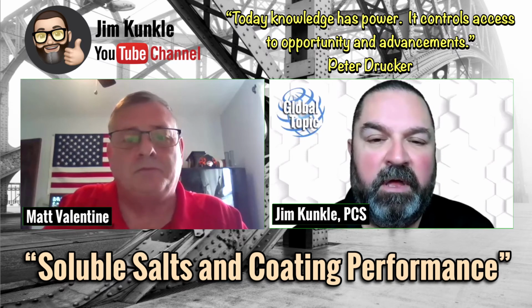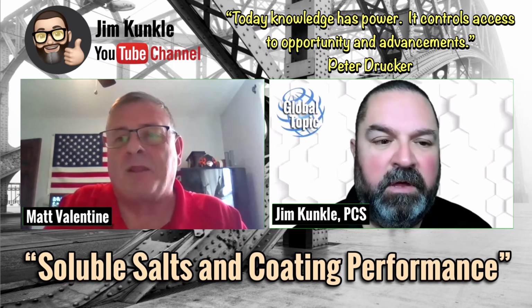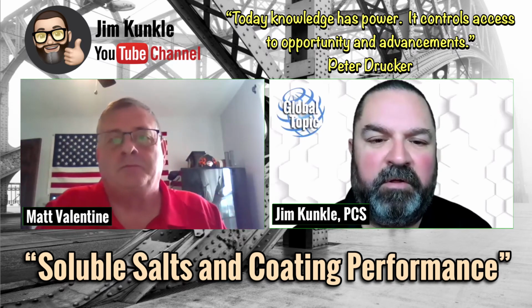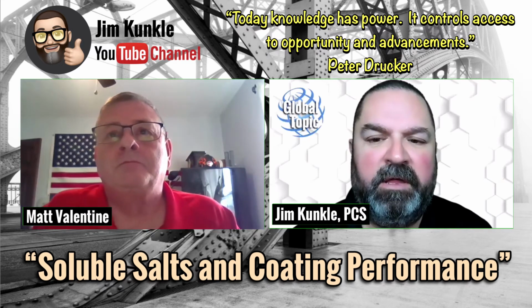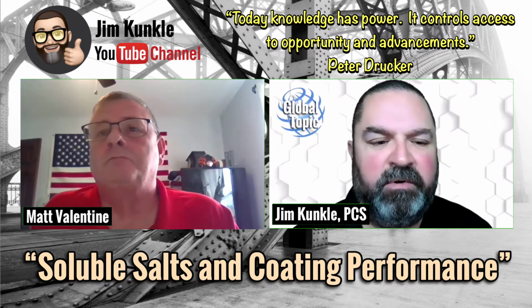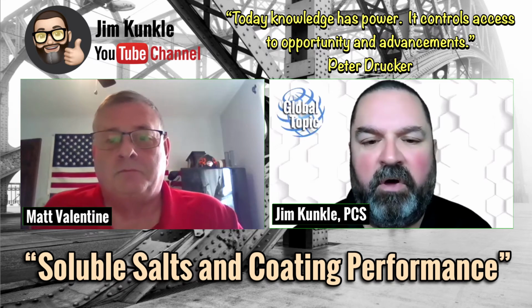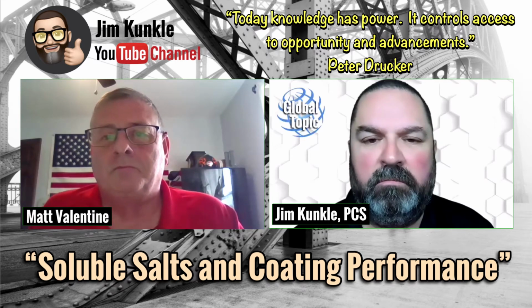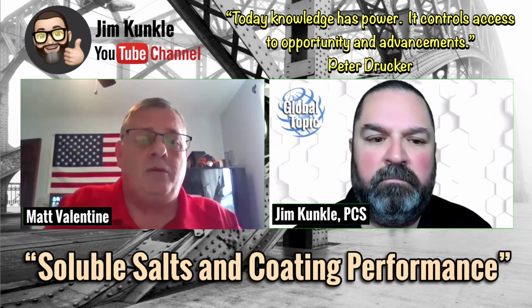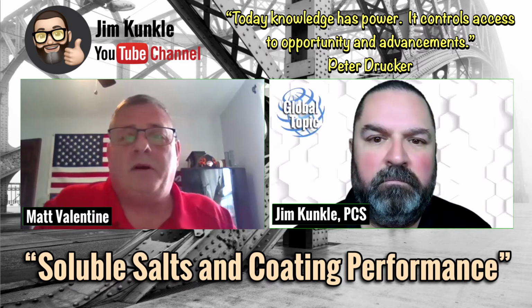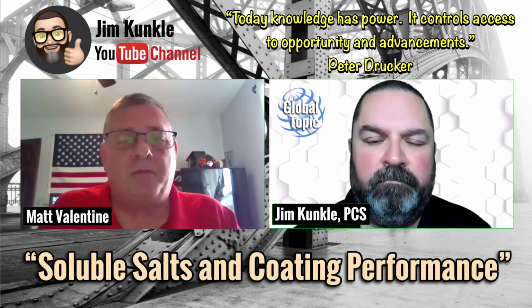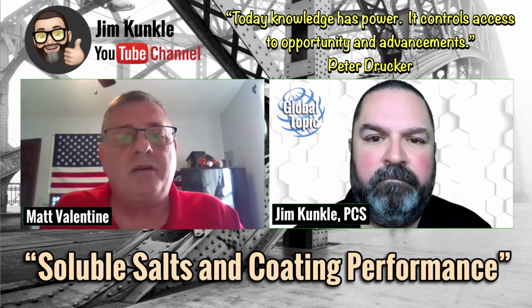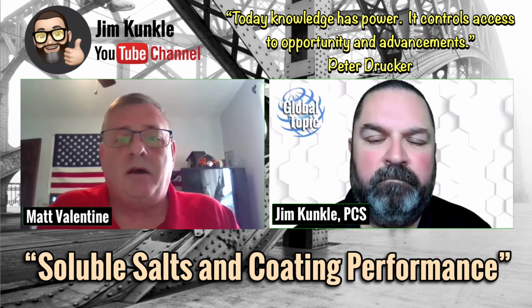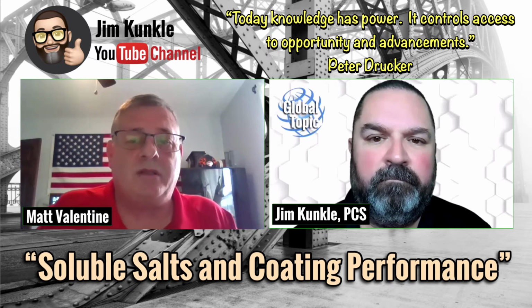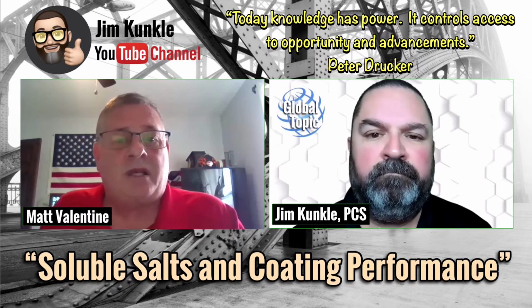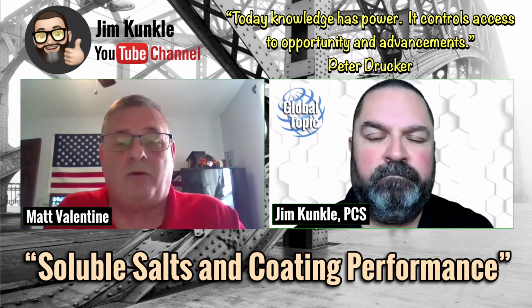Very interesting. So, you've gone through and you've cleaned, can the presence of soluble salts ever be completely removed? Is there any data that shows, by just reducing levels, it's okay for most coating systems to perform well? Definitely. According to a JPCL article that was published in 2001, I believe, Howard Mitchke, who worked for Shell Global Systems at the time, conducted an extensive study on the impact of salts on coating performance.